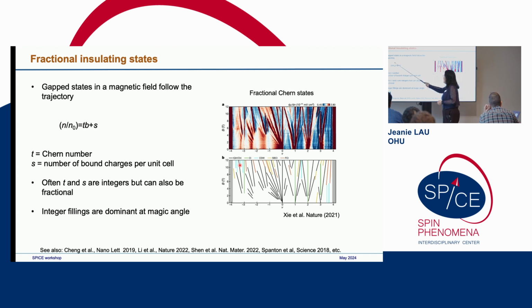Here n over n naught, where n naught is basically the number of charges per superlattice unit cell, and B is the effective magnetic field, the number of flux quanta you can fit into the superlattice unit cell. Now this t, the slope, is basically a Chern number. So the vertical lines are Chern 0, and the sloped lines have a certain Chern number, and s is the number of bound charges per unit cell, corresponding to the intercepts on the horizontal axis. Often these t and s numbers are integers, but can be fractional.